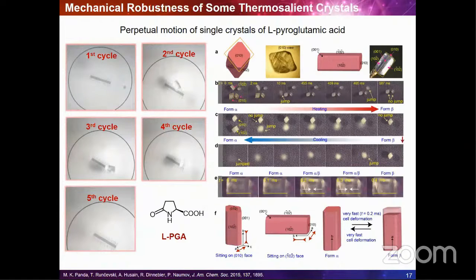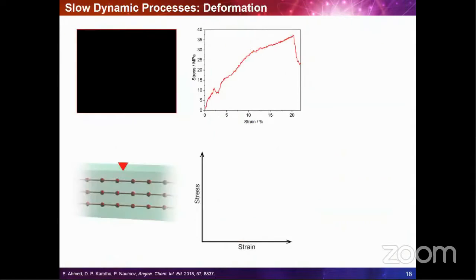So if we miniaturize the thermosalient solids to micro or even to nanoscale, this could further contribute to preserving the crystal integrity. And if we combine this with hydrogen bonds and absence of significant defects, they could be considered for further improvement of the performance in a cyclic operation mode as opposed to single stroke operation. Now I would like to switch gears here to much slower dynamic processes, and in particular crystal deformation, where also the non-covalent interactions play the most important role.